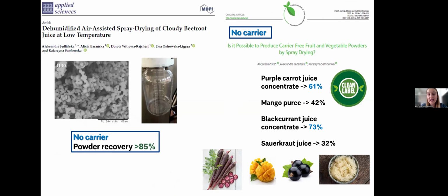As the data that we observed from eliminating the carrier completely, the idea of exploring more materials and see how they will react by removing the carrier using this technique. We as well spray dried the cloudy beetroot juice at lower temperature, which was 130 degrees Celsius. We could as well remove the carrier completely. And over here, once again, we noted very high powder recovery, over 85%.